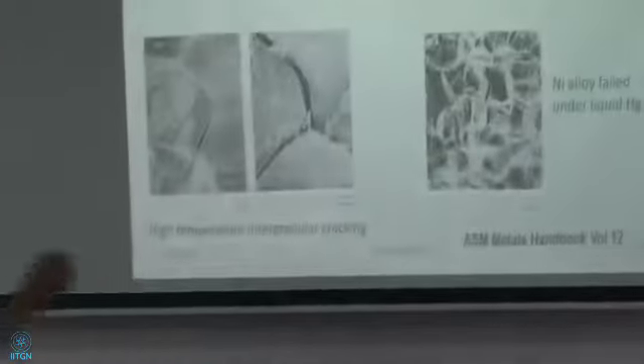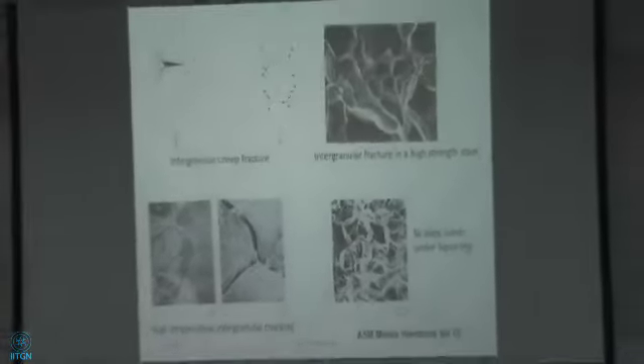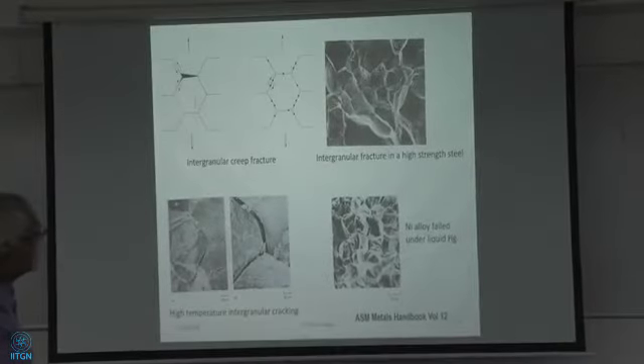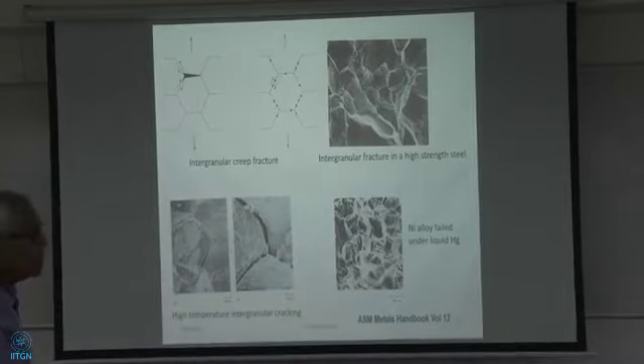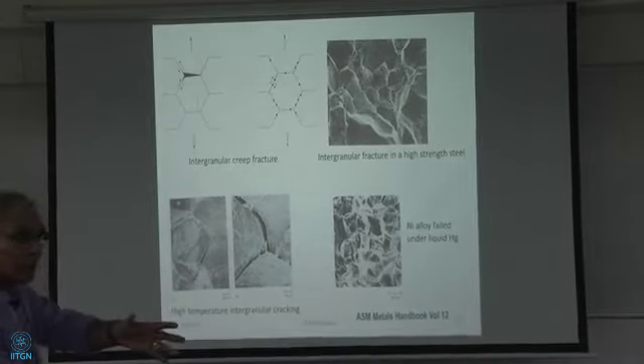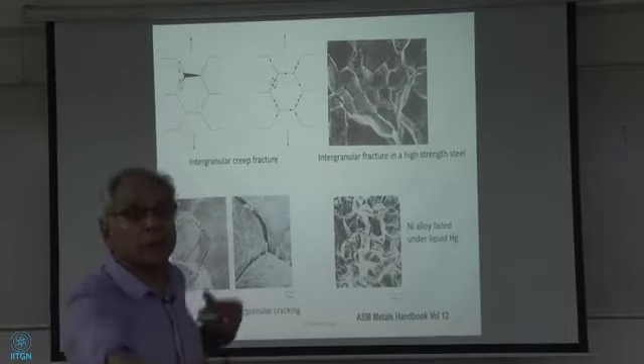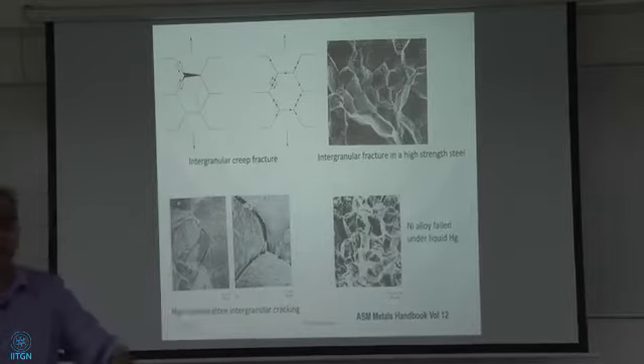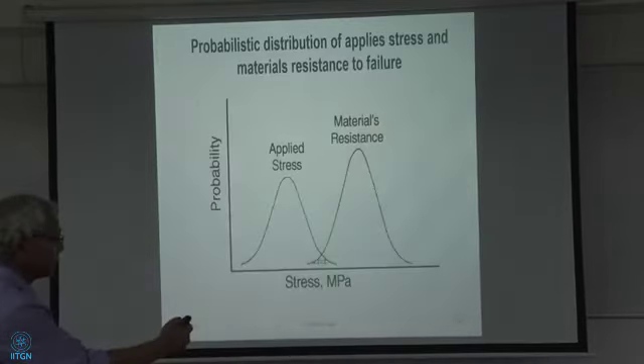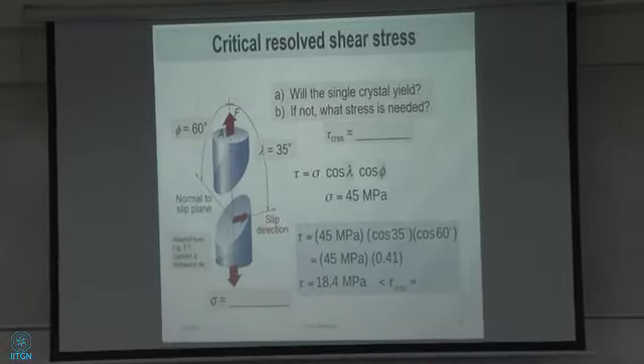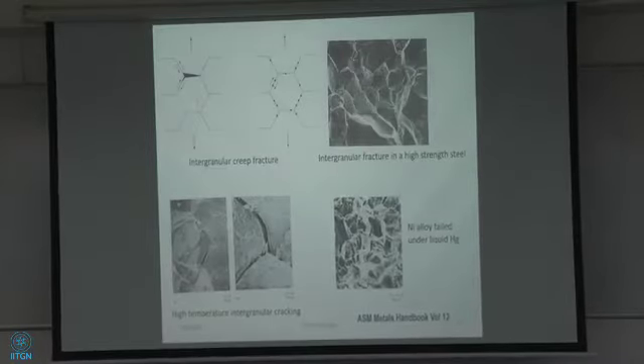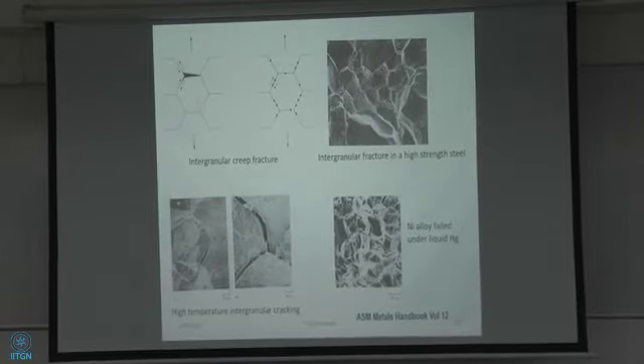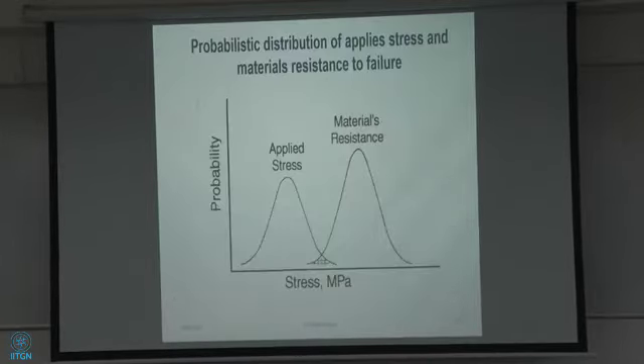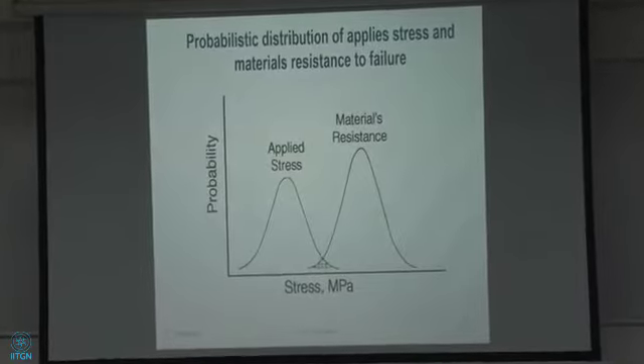So this intergranular creep fracture that you're seeing takes place when you're operating at very, very low stress, no dislocation movement, because there's not enough stress to move the dislocations. But the vacancies can diffuse because the temperature is high enough, so the vacancies will move. Okay. So that's what I just want to introduce to you. We talked about that a little bit. I just wanted to put this picture in because I wanted to convey one piece of information to you.